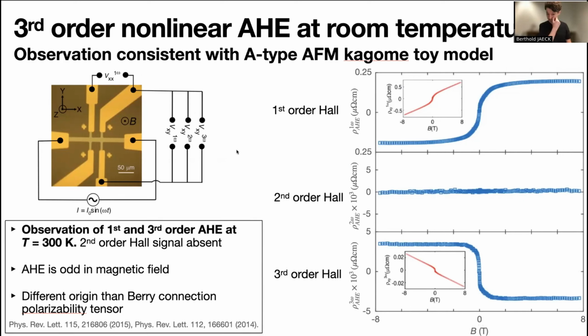Our very first experiment I show you now is conducted at room temperature. What you can see here is the result of these measurements summarized on the right side. We observe a small anomalous Hall effect in the first order response. On the other hand, the second order response is completely absent. What is interesting, however, is that we observe a relatively strong third order response, which is exactly what you would expect from our toy model. We would expect a first and third order response, but no second order response owing to the symmetry constraints.